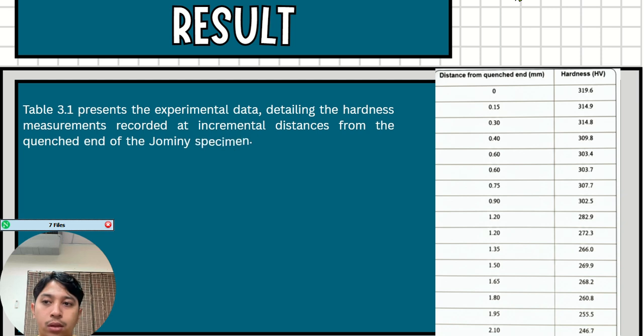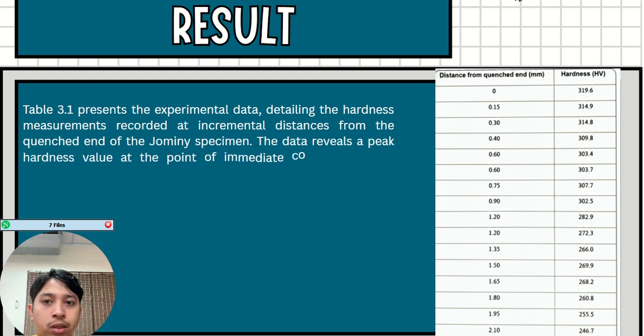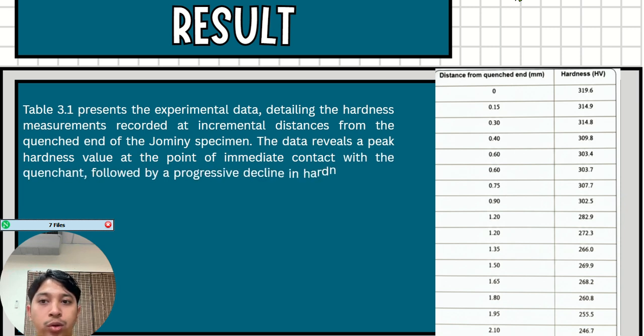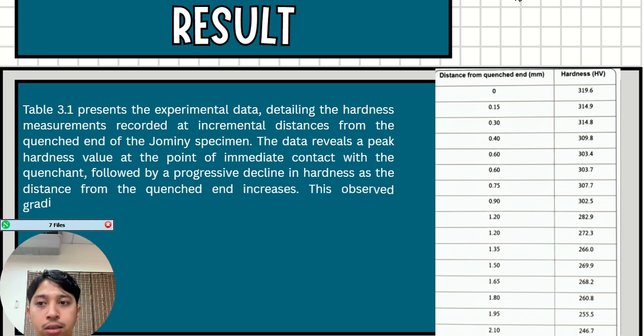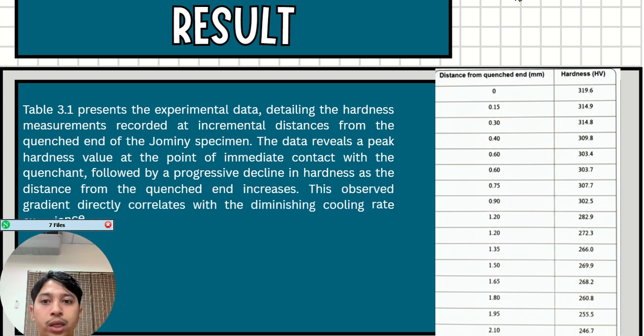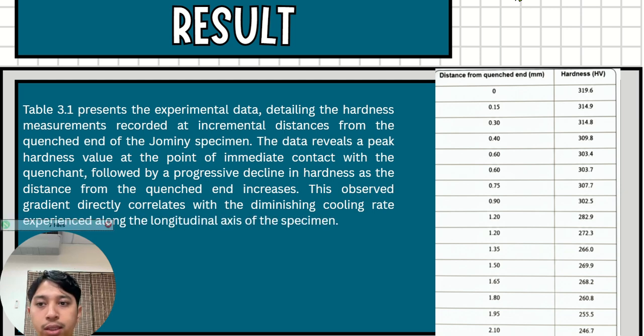Okay, table 3.1 presents the hardness measurements recorded at incremental distances from the quench end of the Jominy specimen. The data indicates that the highest hardness occurs at the quench end, where the specimen is in immediate contact with the quenchant. This is due to the rapid cooling in this region, which promotes the formation of harder microstructures such as martensite.